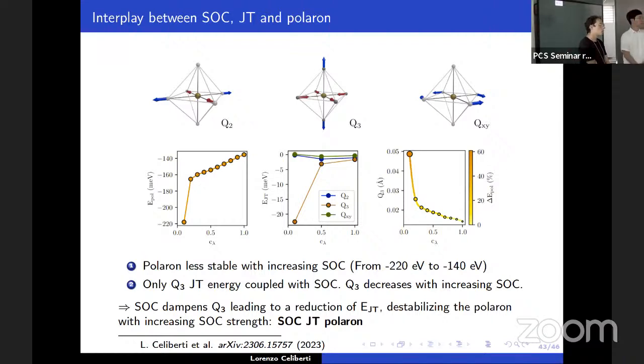Can this quadrupolar dynamic contribute to the dynamic structure factor when you measure muon scattering? You mean the quadrupolar interaction? The dynamic of this polaron, can it contribute? I would say it is possible, but the point is that we don't really know what is the magnetic state of the polaron, because so far we didn't manage to study it.